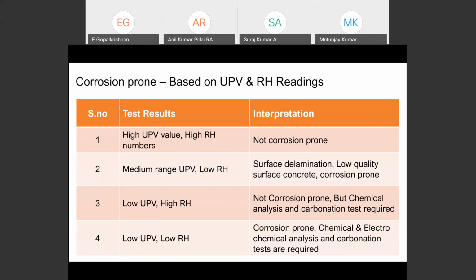How to interpret the result? If you are doing the common tests like UPV and rebound hammer, this will be misleading sometimes if you are not doing the interpretation correctly. When you get a high UPV and high rebound number, it may not be more corrosion. If you have a medium ultrasonic pulse velocity with a low rebound hammer, it could be a surface delamination or low quality surface concrete, or this may be a corrosion prone zone. We need to assess with more NDT techniques.